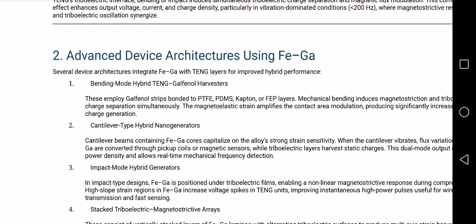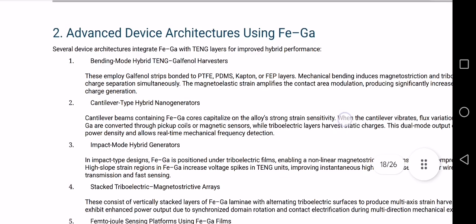Second is advanced device architecture using FeGa. Bending mode hybrid TENG Galfenol devices. This is one of the most common designs. The structure is a FeGa strip bonded to polymers like PTFE, PDMS, Kapton or FEP. In its working, when the device bends, FeGa undergoes magnetostriction. Triboelectric layers separate and contact, and the result is larger contact area change and high surface charge generation.